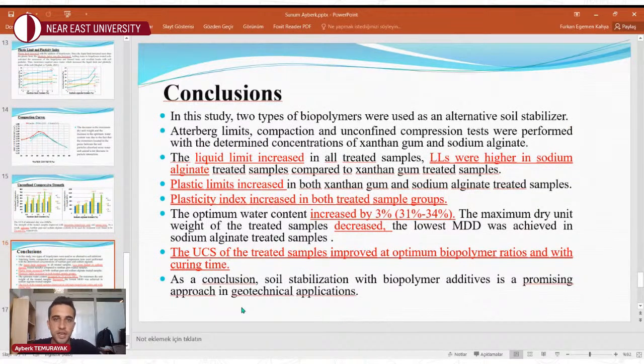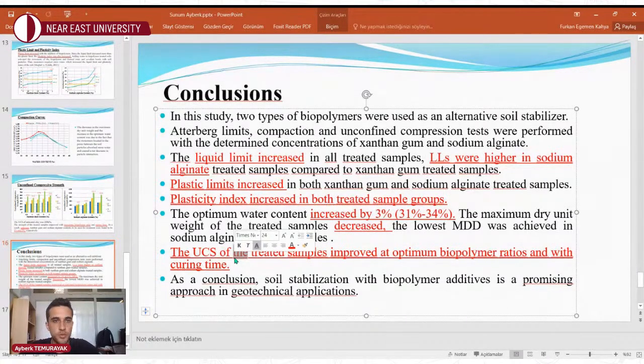In this study, two types of biopolymers were used as an alternative soil stabilizer. Atterberg limits, compaction, and unconfined compression tests were performed with the determined concentrations of xanthan gum and sodium alginate. The liquid limit increased in all treated samples, and they were higher in sodium alginate treated samples compared to xanthan gum treated samples. Plastic limits increased in both xanthan gum and sodium alginate treated samples, and also plasticity index increased in both treated sample groups.